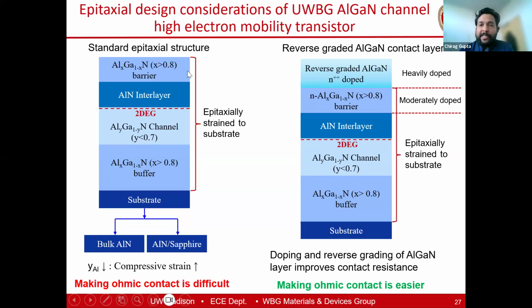So in order to facilitate ohmic contacts, what we do is we add this reverse grade AlGaN layer. The whole idea is basically to give a slightly lower bandgap material so that the metal can form a decent ohmic contact, and then you want to make sure that this layer is connected to the barrier and through the channel in order for the electrons to flow from source to drain. So this is something that other groups have looked at as well, and it seems like this is one of the ways to facilitate an ohmic contact.